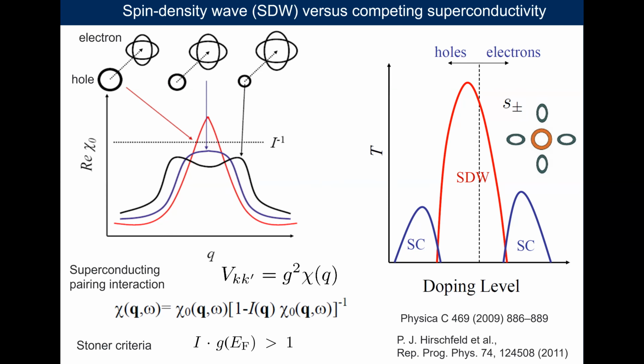spin fluctuations. And the type of pairing expected is S plus minus, meaning the gap will be positive on the hole pockets and negative on the electron pockets. So the wave vector that connects hole and electron pockets will also enable the pairing, and it has to be S plus minus because this type of interaction is not attractive.